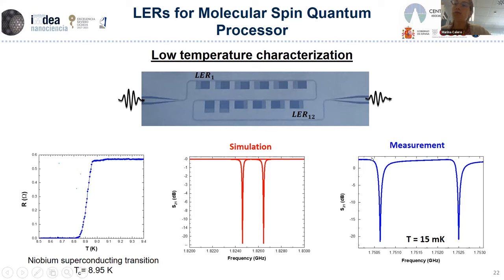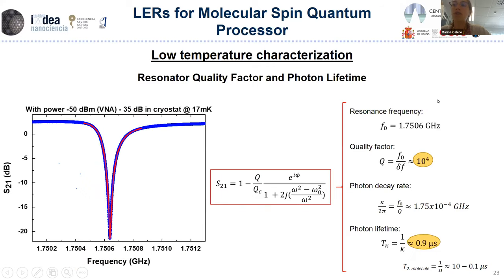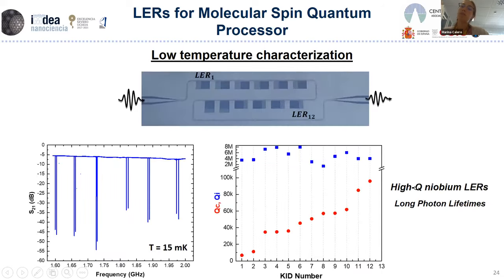If we do an appropriate fitting to each resonant peak, we can resolve our resonant frequency and quality factor, and so the photon decay rate in the cavity and the photon lifetime. As we can see here, we achieve high quality factor resonators with long photon lifetimes. With just one frequency sweep over all the chip, we can resolve all the pixels, where each minimum in the transmission signal is related with each pixel.